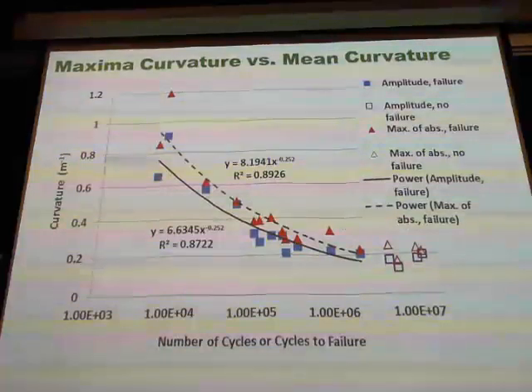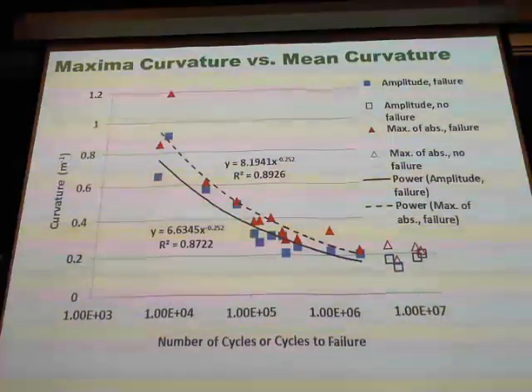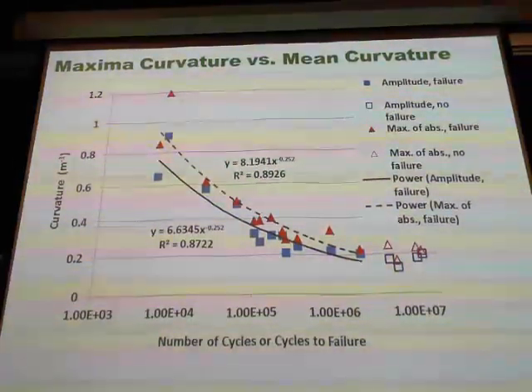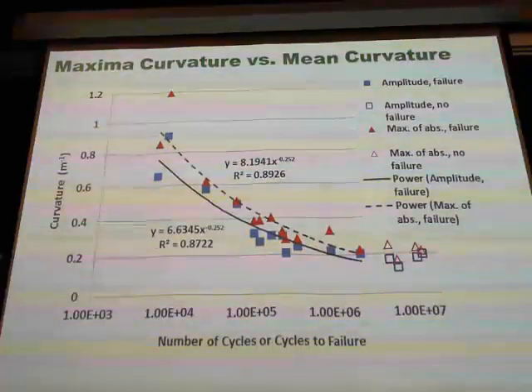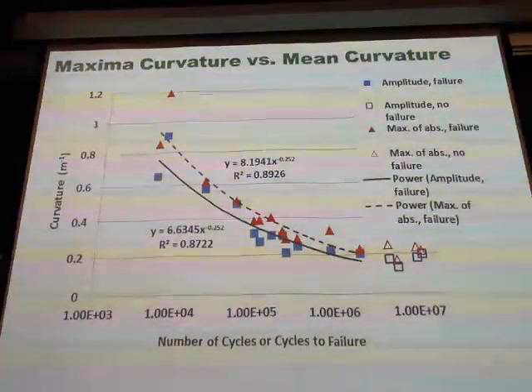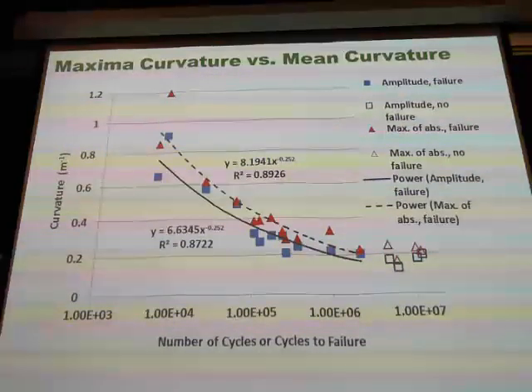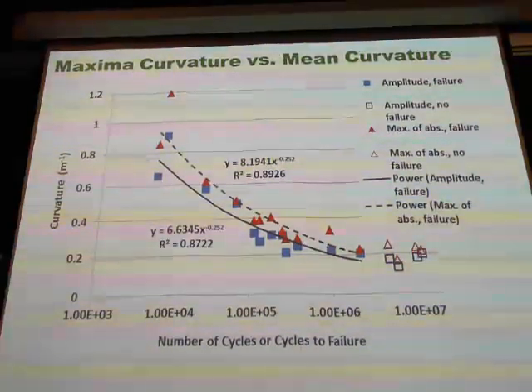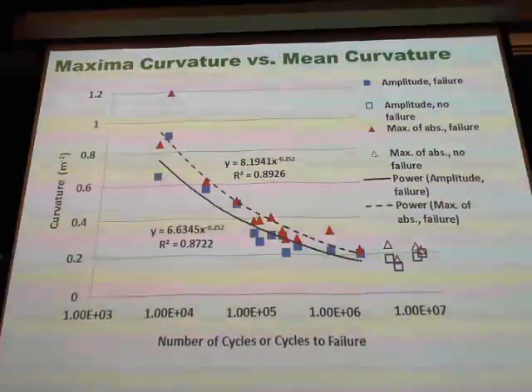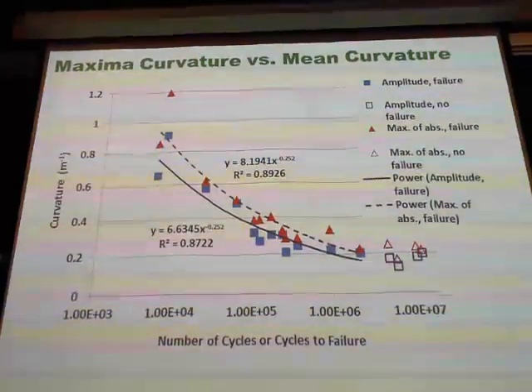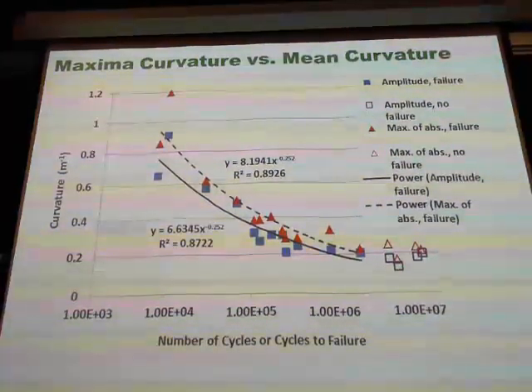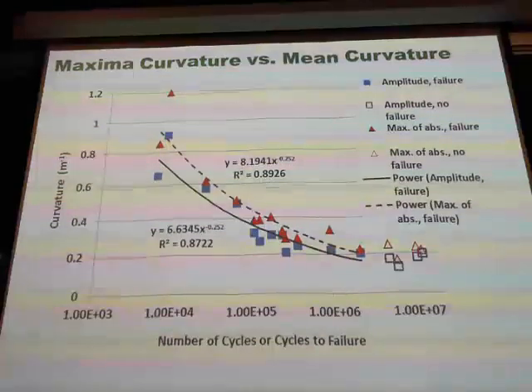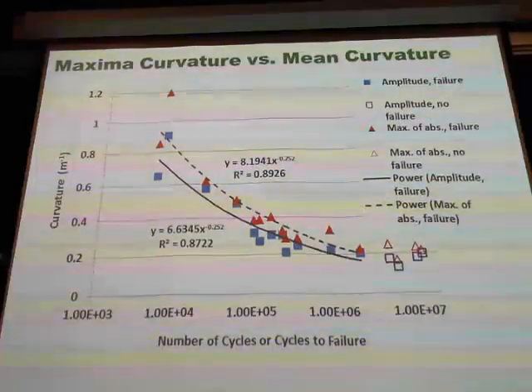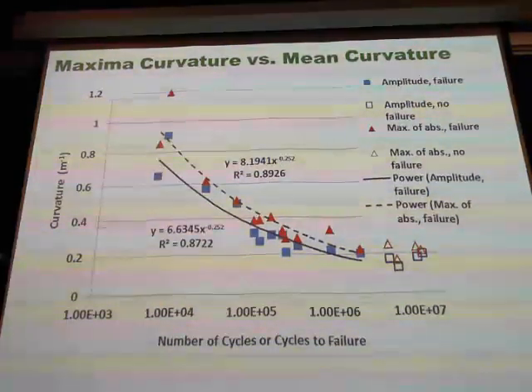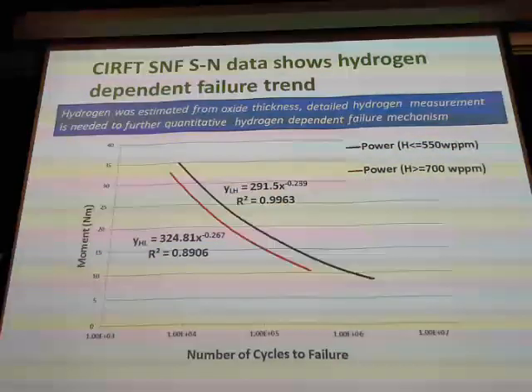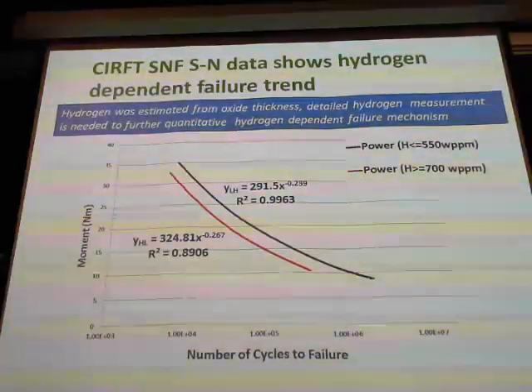Again, I want to mention that in most fatigue testing, the stress is uniform across the cross section. But when you do flexure bending, it's not. It's like triangular, a very high stress gradient, with zero in the middle. So you cannot compare flexural fatigue strength with your uniform tension-compression sample. This needs to be borne in mind. This would also apply to heat exchanger tubes and tube vibration.